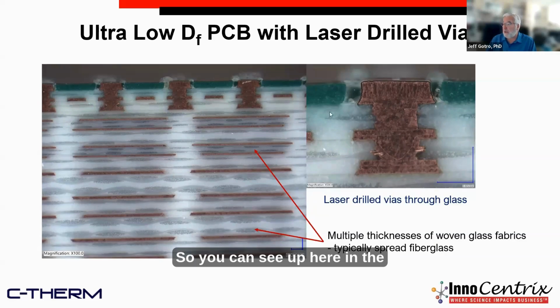So you can see up here in the vias where these layers are really thin, they use very, very fine woven glass. Down here in the core, they have much thicker. In this cross section, right where my arrow is, the weave is coming out at you, and then these are the yarns that are going in the Y direction, and then the yarns, these ovals, are coming out at you. But you can see various different sizes of the glass cloth from the center core out to the fine surface on the outside.